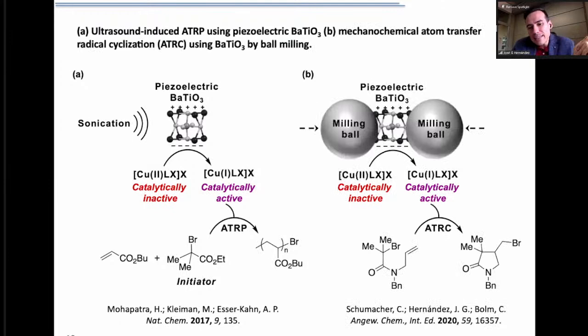So we wanted to see if we could use the mechanical deformation that collisions of balls or the ball within the container could cause on barium titanate to create those regions in which you have charges. And we demonstrated that indeed, by ball milling, you can also activate piezoelectric materials so that a reduction can be promoted, and then you might end up with a catalytically active species for a reaction. In this case, it's not a polymerization reaction, it's an atom transfer radical cyclization reaction.